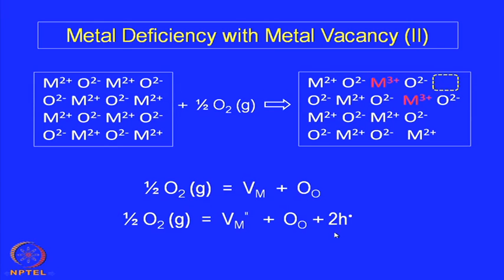So, we have positive charges getting added to the 2 plus sites, one each to two different metals, and that is how you are creating two M3 plus sites, and they are variable valency, they can change any time. In fact, it is a kind of resonating valency. That means, all the time they are not 3 plus. Because the hole is a mobile species, when it is getting attached to this, then it becomes 3 plus, next time it will be once again 2 plus.